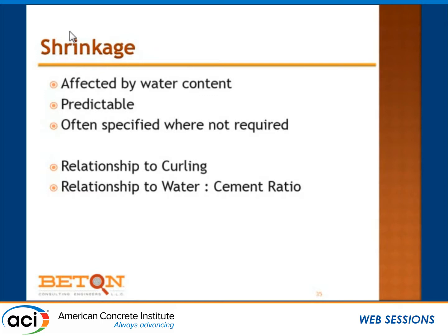So we specify a water-cement ratio of 0.4, but 600 and 240 and 800 and 320 are both 0.4 water cement ratios, and one of them will have a shrinkage that is at least double of the first. Both of them are in compliance with the specification. Then you get a lot of shrinkage cracking and curling, and everybody comes back and says the concrete wasn't what we needed. Back to your responsibility: what's the role of the concrete producer to stop the engineer from doing something that she may not have intended.